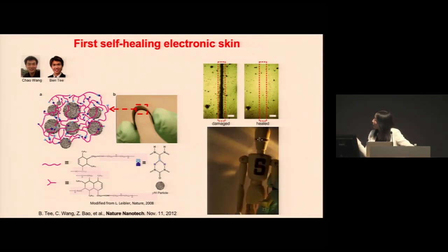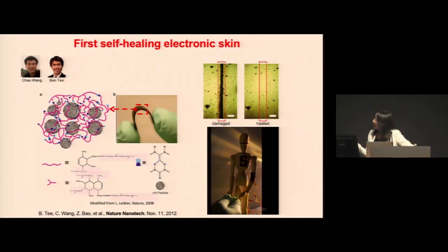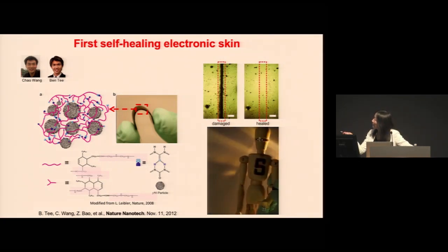So the first generation of such material that we work with is this polymer network that's cross-linked together with these urea-based hydrogen bonding. The urea groups allow the breakage of this network when the material is under strain. And this material can self-heal when there's a scratch being induced. Because of the dynamic nature of this polymer network, the polymer can diffuse across the cracked region, and the chemical bonds can be reformed.